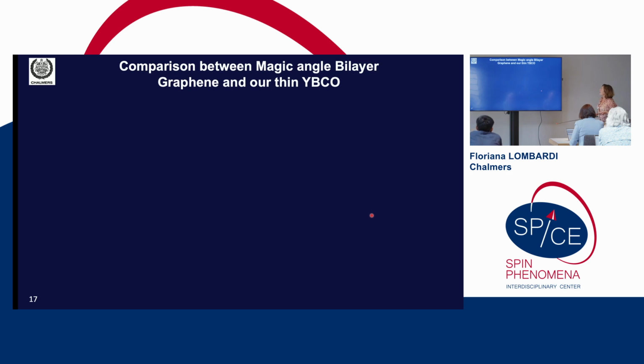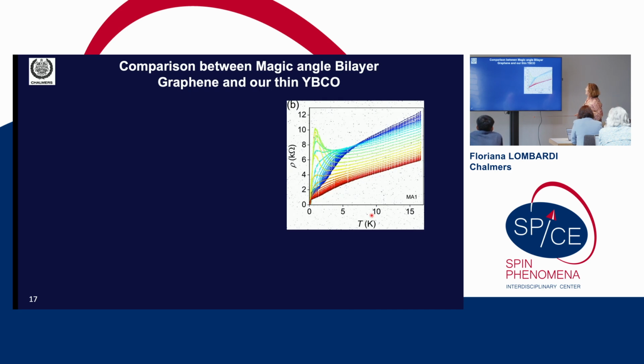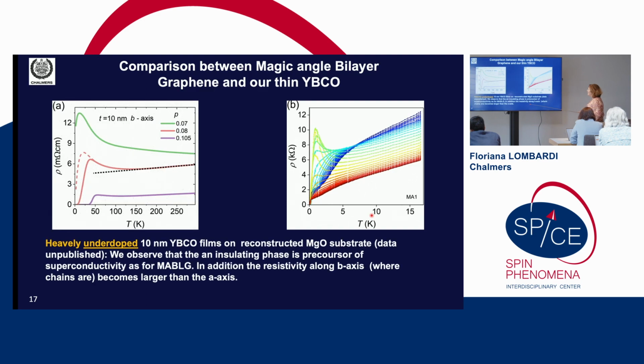And this goes almost to the end, because what we have further studied is whether in our film the analogy with magic angle graphene could be pushed forward. I told you that in these materials, at the magic angle, you have strange metal, correlated insulator, and superconductivity. In our film, what we have is linear-in-T strange metal precursor to superconductivity. But will we get anything like this in our thin films? And the answer is yes.